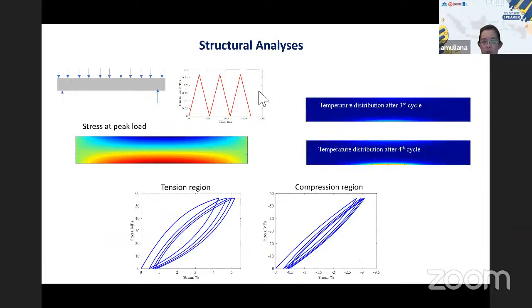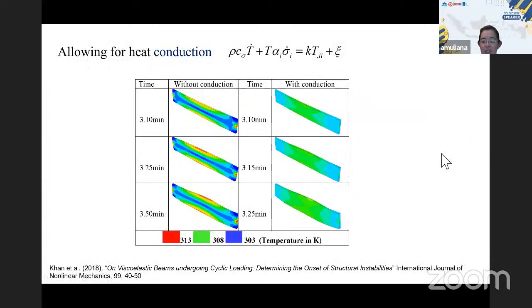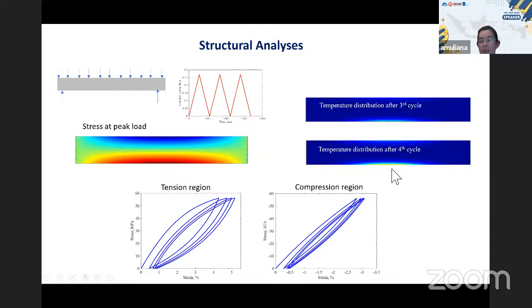When we look at this in a structure, this is just a simple beam, right? Under loading, unloading, and reloading, unloading. This is the tension region, and this is the compression region. When we look at 3 or 4 cycles, you already start seeing heating. This is what we call a hot spot, right? This is the temperature distribution after 4 cycles. We start seeing higher temperature. Now, when you continue for a larger number of cycles, you'll see more and more energy being dissipated, and it would generate more and more heat.